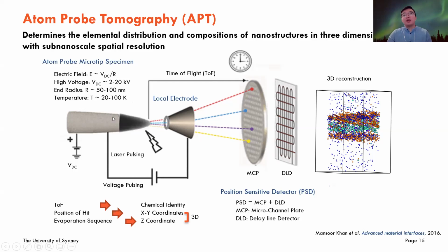When we put the sample here, we apply a voltage pulsing field between the sample and a so-called local electrode. And sometimes we add a laser just to assist the atom evaporation. I think that's excellent for bio and semiconductor materials. And the atoms will fly and then be detected by the PSD detector.